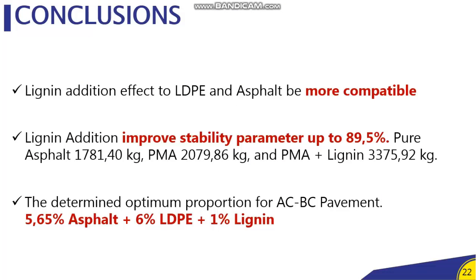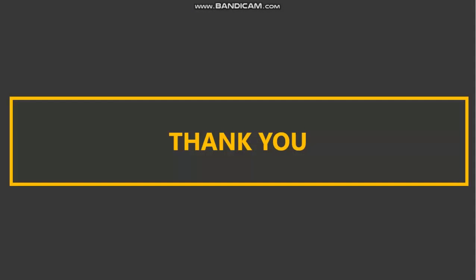And this is the conclusion of our research. First, lignin addition makes LDPE and asphalt more compatible. Second, lignin addition improves the stability parameter up to 89.5%, and the determined optimum proportion for AC-BC pavement is 5.65% asphalt and 6% LDPE plus 1% lignin. Thank you very much for your attention.